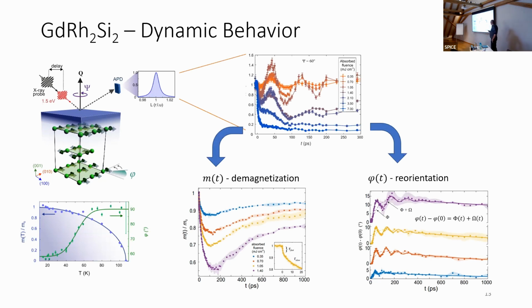And essentially what tends to be understated is that this is a parametrization of a solution of the spin structure at every single delay. So at every single delay, we have quote unquote crystallographically solved the spin structure. And we can say where every spin in the unit cell points at every single delay, in this case for 4 different fluences. And of course, you can see that more is happening than just a shift. So the baseline here is this shift, which we see also statically in equilibrium. And we have this wiggle on top, which is a displacive excitation of the local magnetic potential of every spin, which I will discuss a bit later.